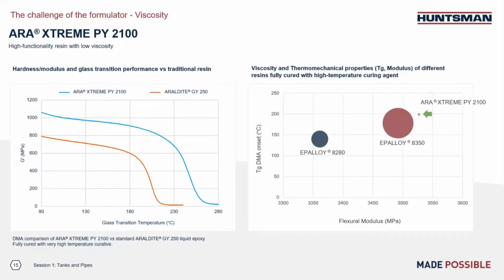And if we compare PY2100 with Novolac on the right side, you can see with this high temperature curing condition and curing agent we use, by using PY2100, we can have a TG as high as close to 200 degrees C. And it's even higher than high functionality Novolac, such as Epalloy 8350. The TG is about 180 degrees C. And if we compare with low functionality Novolac, such as Epalloy 8280, the TG is even below 150 degrees. So that's a huge TG difference here.